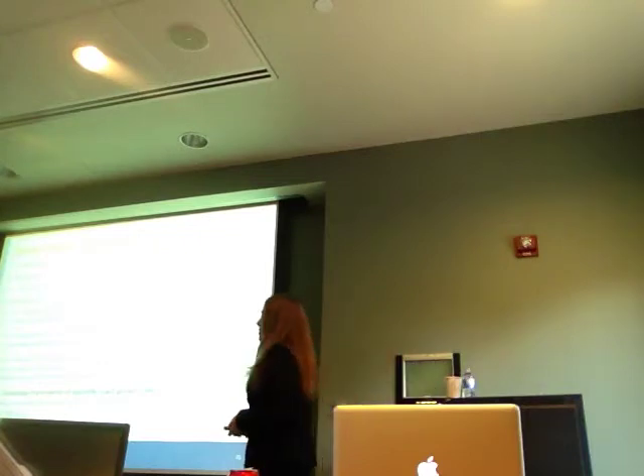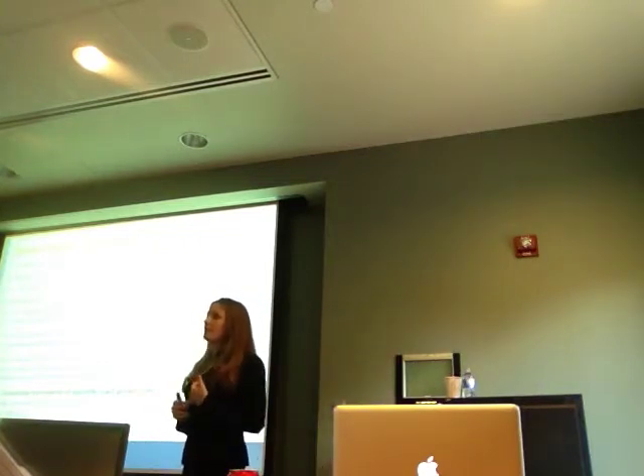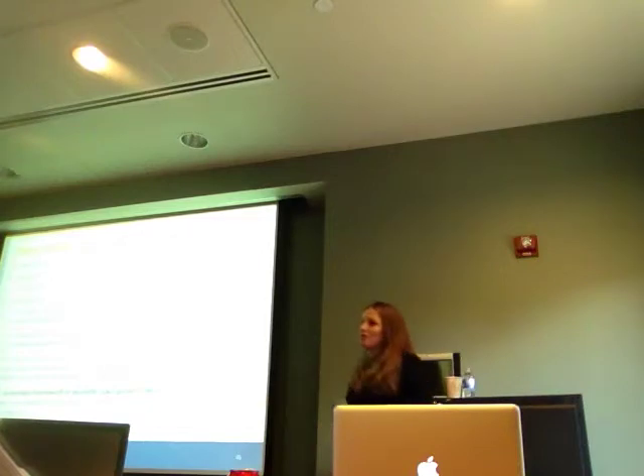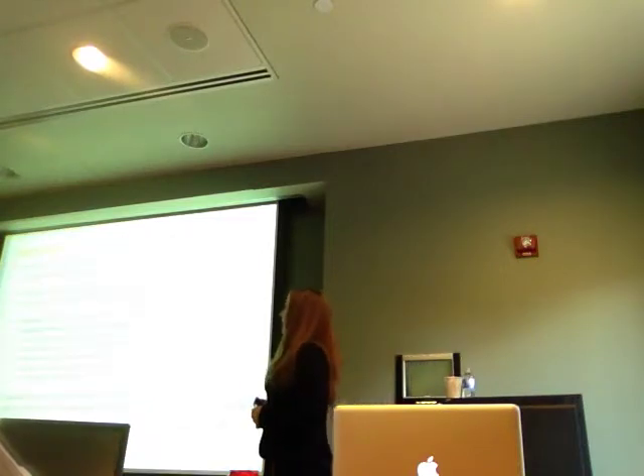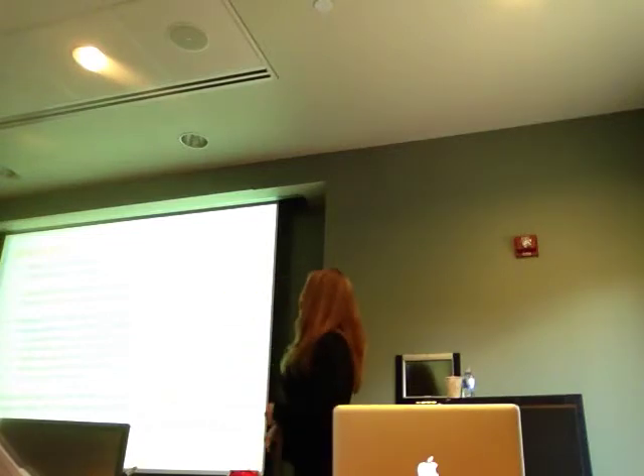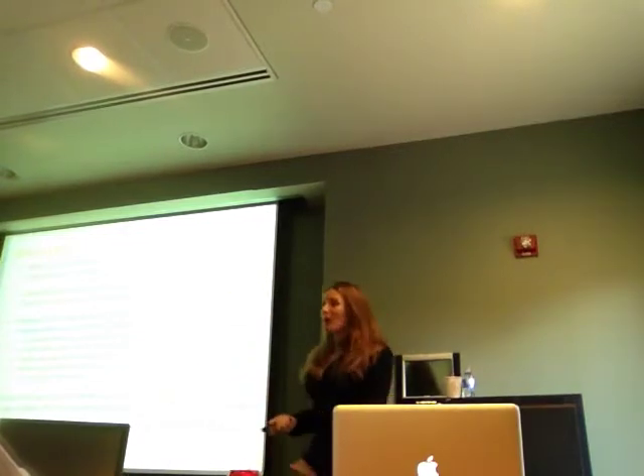So with that, we can show that crack growth rate is controlled by your hydrogen diffusivity, as well as your crack tip chemistry. And these are my conclusions. I can walk you through them.